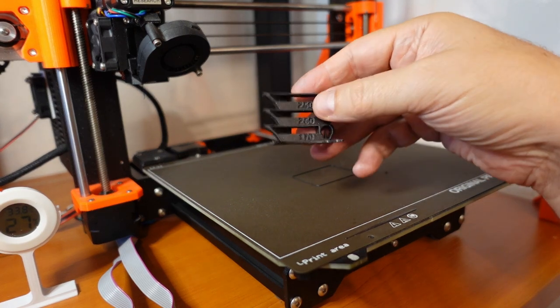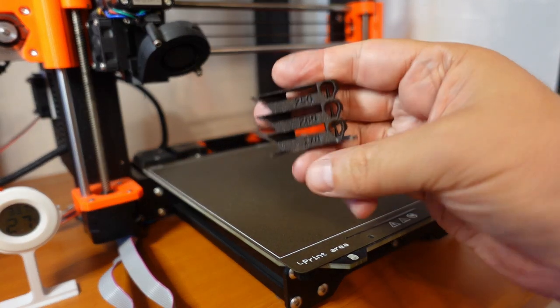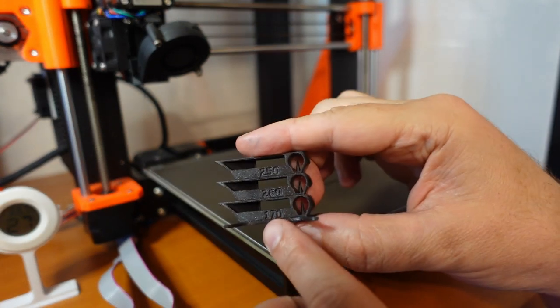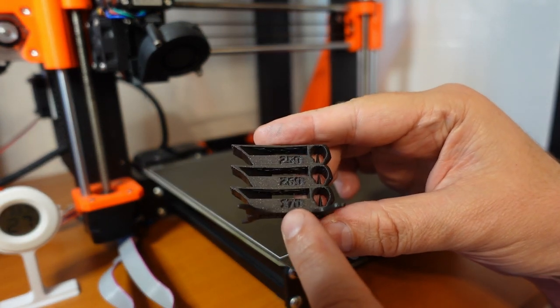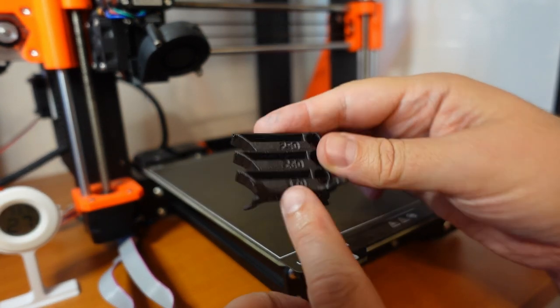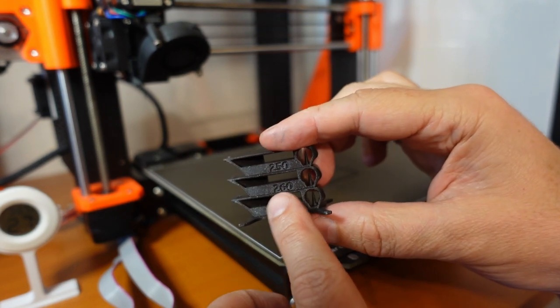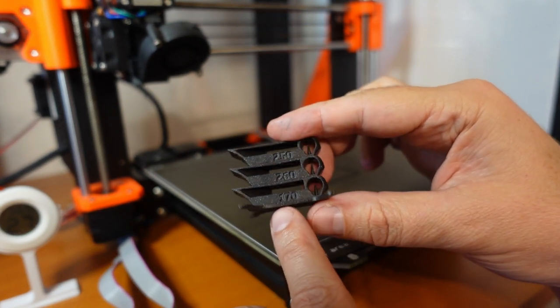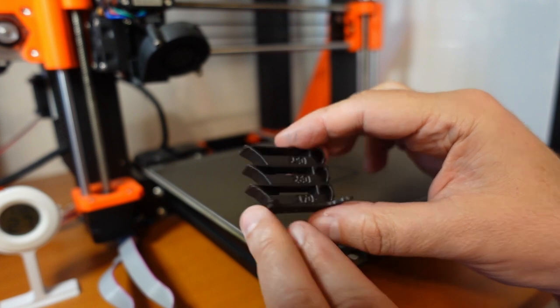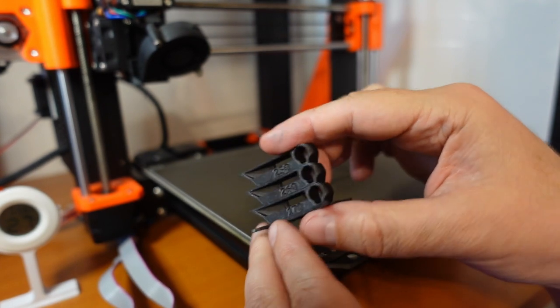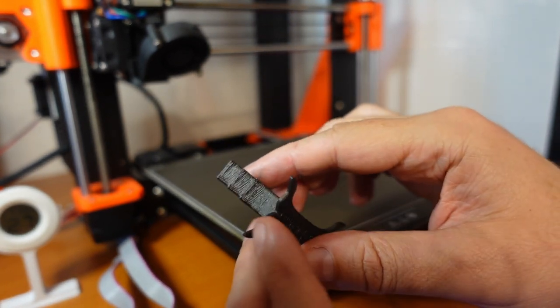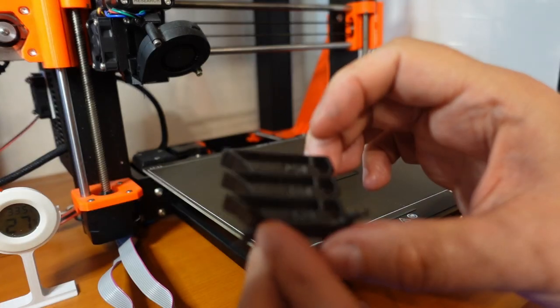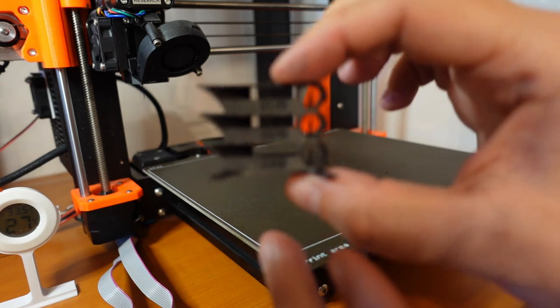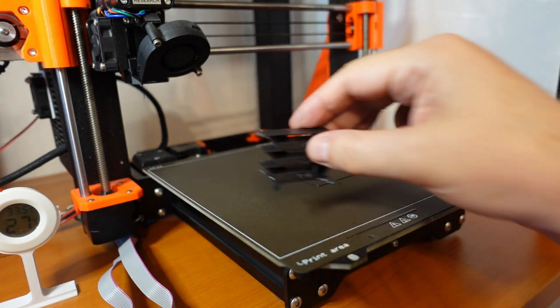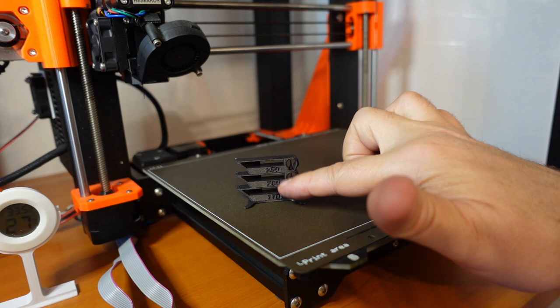And it looks like we have another almost perfect temperature tower. Don't be confused, this is 270 degrees Celsius, only it looks like the guys didn't predict that anybody would print above 260 degrees Celsius. So they didn't prepare that element. Great overhang even at 60 degrees, interesting, perfect bridging, and of course absolutely no stringing. Okay, I think it's time to print test specimens at 260 degrees Celsius.